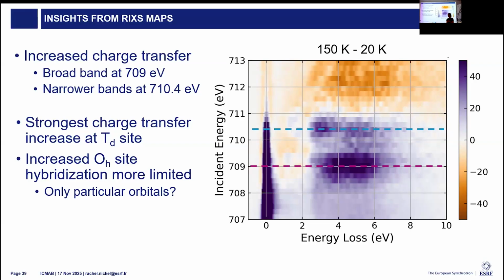We can tell in the band gap region if there is a shading that shouldn't be there. So it's mostly paying attention to artifacts. In the elastic line, we can see that the difference between the edge, so this is where it really should be a pure elastic feature, there isn't a difference.